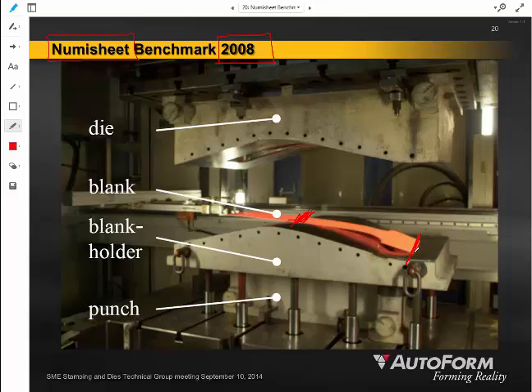And therefore, when we talk about hot stamping, we've really seen that this idea of hot stamping, hot forming is something that's going to be very reliant on our ability to engineer and mathematically simulate these forming operations in order to assure that we get the product characteristics that we finally wanted. Because it is possible that this early contact in these different areas of the blank, or even where we're holding it with whatever robot or automation is loading that blank in, any initial contact could cause the material to cool at a different rate and not quite get the material properties that we were aiming for.